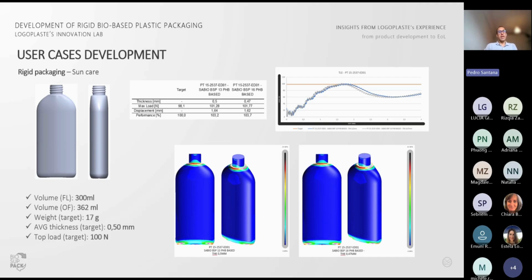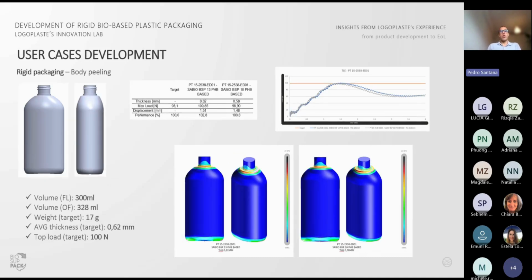requirements. In this specific case of the SunCare packaging, an average wall thickness of 0.5 millimeters was achieved, with a total weight of 17 grams, ensuring a minimum top load of 100 newtons. These values fall within the capabilities of the available equipment and are consistent with the typical parameters for packaging of this type. The same methodology was applied to the remaining packages or case studies of this project.